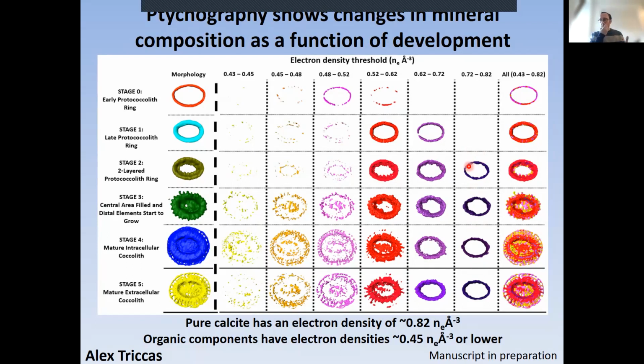approaching that of calcite. It only forms the core of the structure and only the center of the ring, and everything around it will start going lower and lower and lower in electron density, and especially when it comes to the calcium carbonate, to the crystal struts that are pointing out. So that means here 2 things. I mean, one is that there has to be some kind of maturation process or changes in composition that is happening. And what I mean to say here is that the coccolith is not purely calcite, which is very surprising,